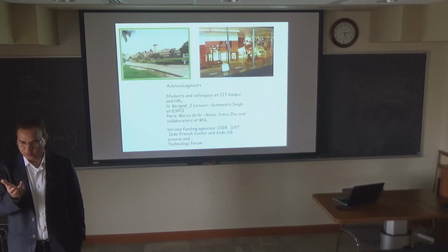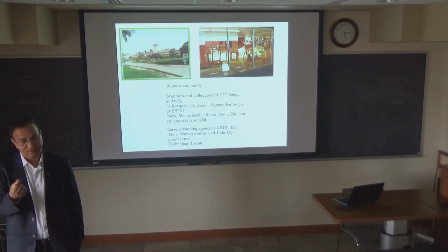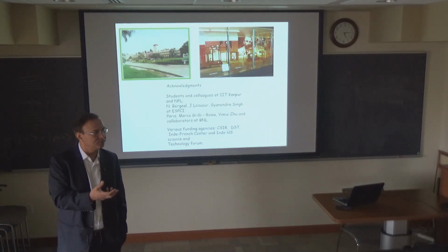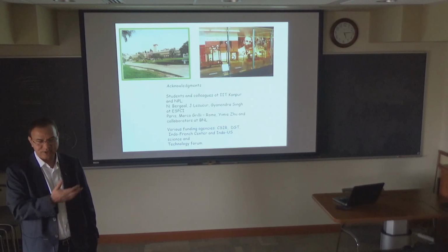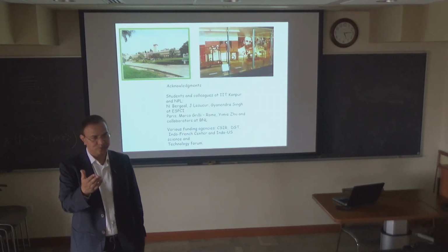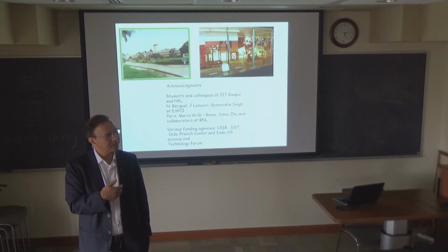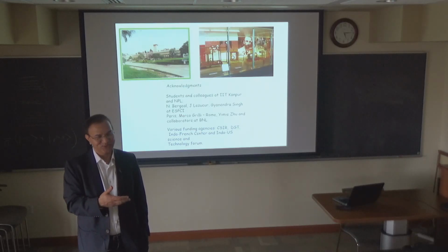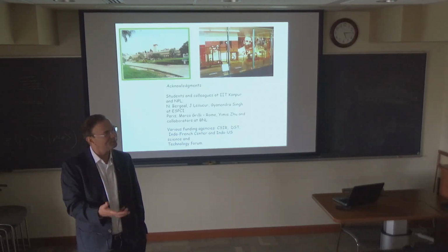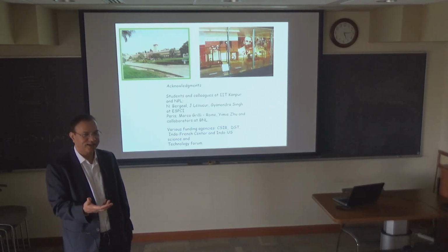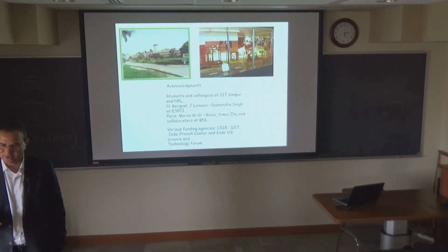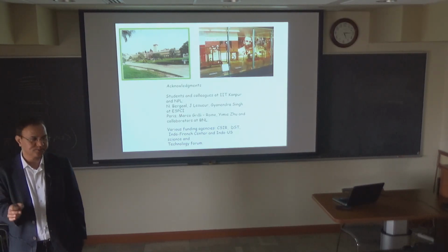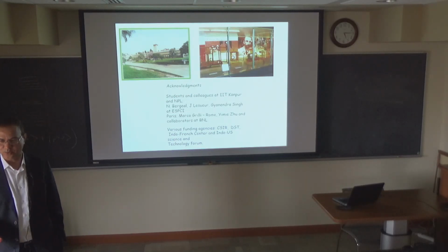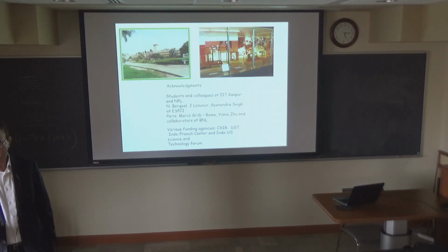Otherwise, magnetism may show something, but the titanium d1 in LTO is an antiferromagnet, and it doesn't seem to affect the superconductivity. Superconductivity looks exactly the same. This French group earlier were getting their LAO/STO samples from somewhere else, but then we started making samples at NPL, and they like our samples more. It turns out the superconductivity in LAO/STO is also exactly the same. So that's why I feel that all the action is happening on the strontium titanate surface, and the dielectric constant of strontium titanate is playing a very important role because it just blows up as you go down. But it's field dependent. It decays very fast as you increase the electric field.